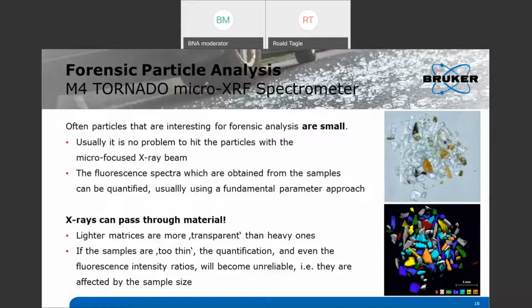The main problem also addressed there is that these particles are small. While micro-XRF usually has no problem hitting the particles, which are usually larger than 20 micrometers in size, we might be running into problems with the thickness of the particles. Both the quantification as well as the net peak intensities, which can be used for classification, need a certain thickness of the sample in order to be representative for the sample.